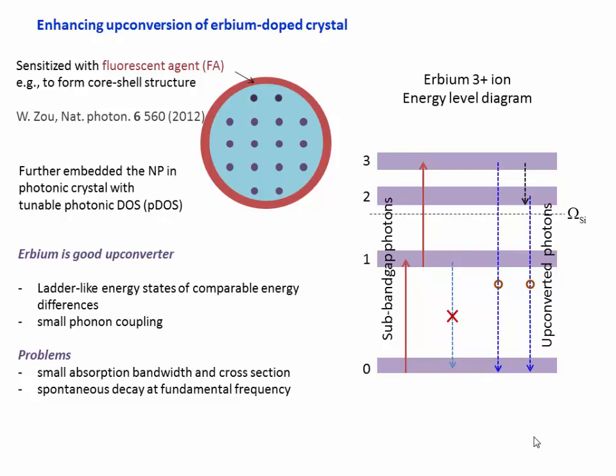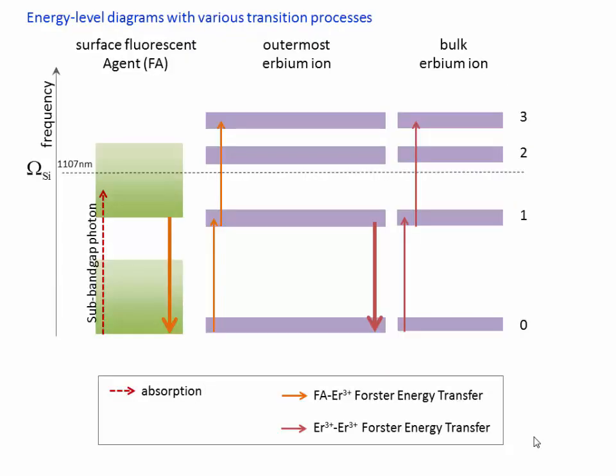And in our work, we would like to get a theoretical examination of this upconversion process, and also we would incorporate a tunable photonic density of states, such that it can suppress this unwanted spontaneous emission at the first excited state of the erbium, and boost the efficiency.